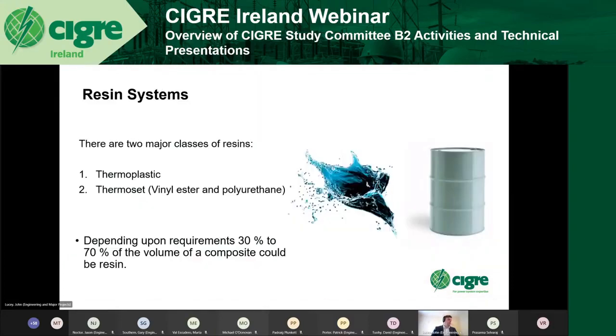The resin system, the thing to note is typically there are two major classes of resin. There's the thermoplastic resin and thermoset resin. The thermoplastic resin is pliable or moldable above a specific temperature, so you can reform it, whereas the thermoset resin, it sets and that's it. Typically it is the thermoset resin that's used for transmission structures. Depending on the requirements, typically anywhere between 30 and 70% of the volume could be resin, and vice versa for the fibres. Typically for overhead line structures, you tend to try and keep the fibre content quite high because it gives you the material properties you want.